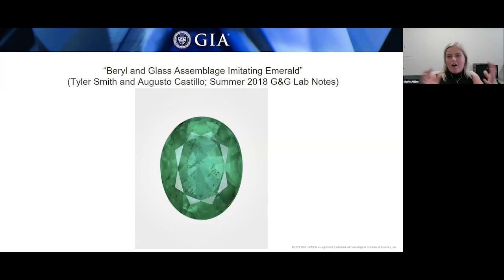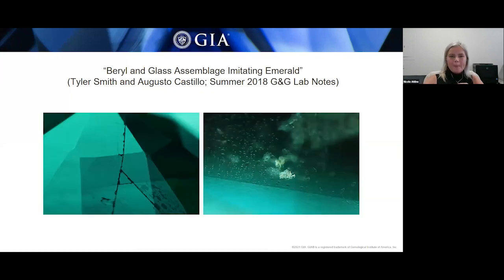An RI was taken over all 5 segments, 4 in the pavilion and 1 for the crown, and it gave a refractive index of 1.61 and an SG of 2.66. Where all these pieces came together, there was a weak white fluorescence that followed those cement planes. Here on the left we can see where areas of the cement planes are intersecting on the pavilion. The photomicrograph on the right shows natural dendritic flakes and fingerprints in that natural beryl section that makes up the core. Large gas bubbles were also observed in those cement layers.